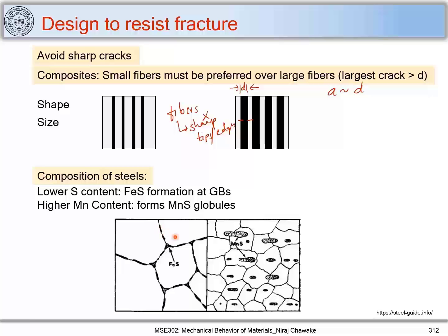Now, how to deal with such a situation when you have a large amount of sulfur? What we do during steel making is add a higher amount of manganese. Manganese has more affinity towards sulfur than iron, so it forms globules inside these grains, not at the boundaries, and thus it reduces the susceptibility of this steel to form cracks at the boundaries and their propagation through boundaries, and thus avoids any brittle failure or catastrophic failure.